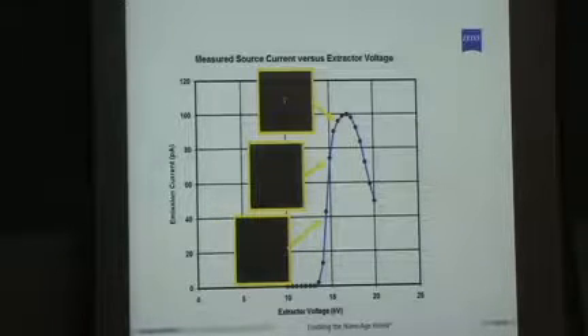As you get closer and closer to the optimal operating voltage, they get brighter and brighter. Beyond that peak brightness, the operating condition we like to operate at, the electric field gets big enough that the next shelf starts to turn on. And now you're starting to share your helium again. You're sharing it with more and more atoms, so each one of the ones you care about is less bright. As you go higher and higher, they actually get a little bit blurry, because the electric field is now ionizing off the surface of the atom. And as you go higher, you even start to pop off those atoms and you get this rounded end form.